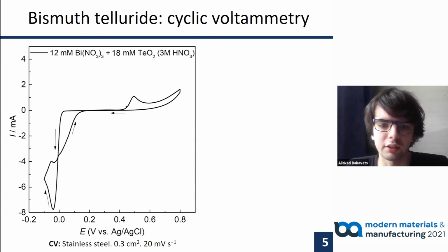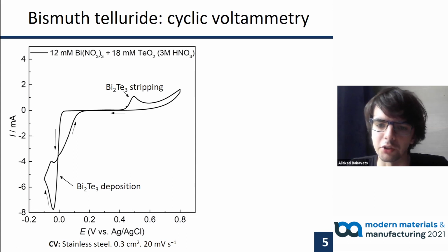This slide shows cyclic voltammograms for the electrodeposition of bismuth telluride from the solutions of its precursors and the subsequent anodic oxidation of the electrodeposits. The film deposition is a reduction process and it proceeds at negative potential. Bi2Te3 oxidation proceeds at more positive potentials.